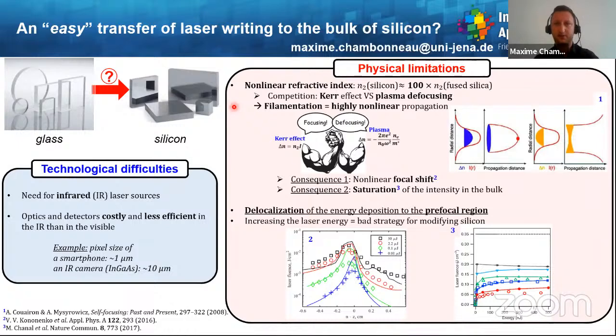And this filamentation regime has two major consequences. First of all, there will be a nonlinear focal shift, as you can see here on the bottom left. For low pulse energies, the beam is focused here, and then when you increase the energy, the focus shifts upstream of the laser. The second consequence is a saturation of the intensity inside the bulk, which is shown here on the right.